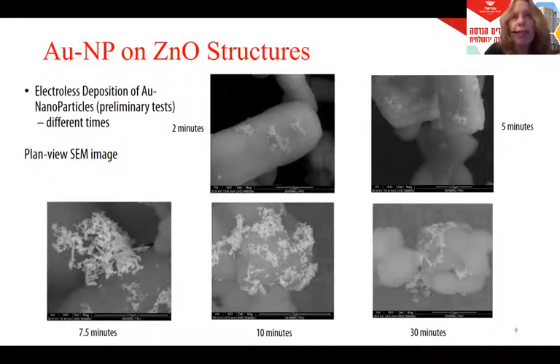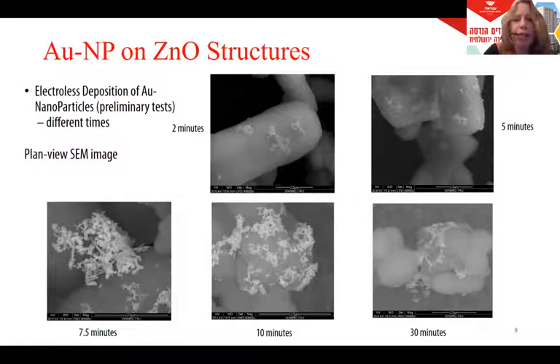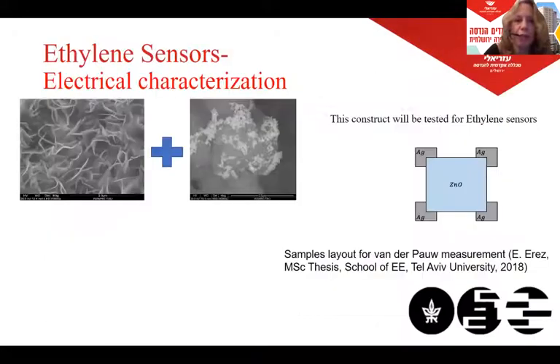However, we studied the deposition rate of gold on nanoparticles, and we will repeat it now that we know how to make good nanowall structure. Now we can do it on the nanowalls themselves. And we concluded that the best time was 10 minutes, but we'll have to repeat it on the nanowalls. We don't know if it's going to be the same times exactly, because the surface area is very different.